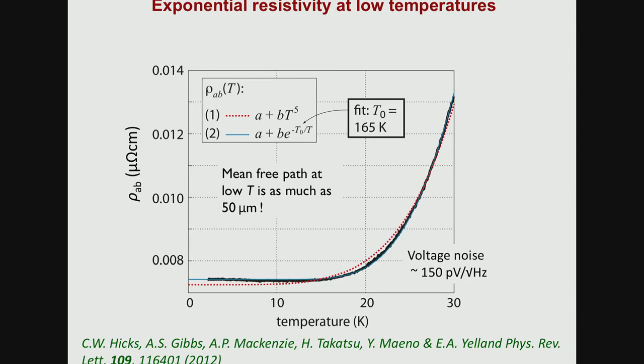So if you look very carefully at the resistivity of palladium cobaltate at low temperatures, this is what you see. The resistivity, if anything, may even drift up a little bit at low temperatures, which isn't implausible in a hydrodynamic situation. But by and large, it's more or less completely temperature independent below 10 Kelvin. And then it turns on.